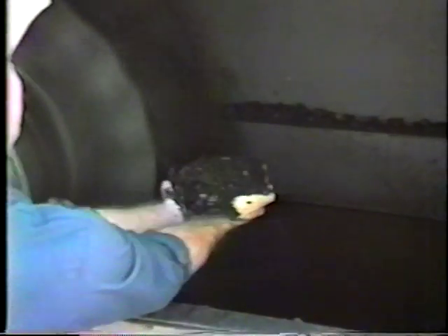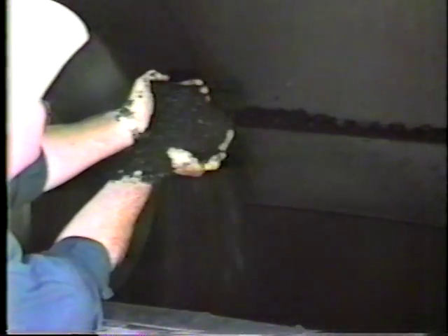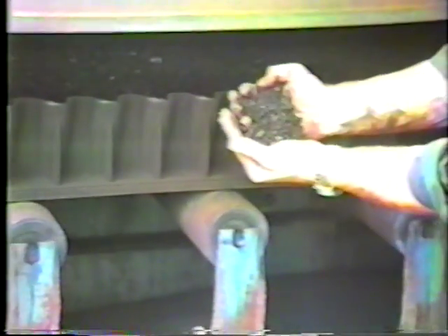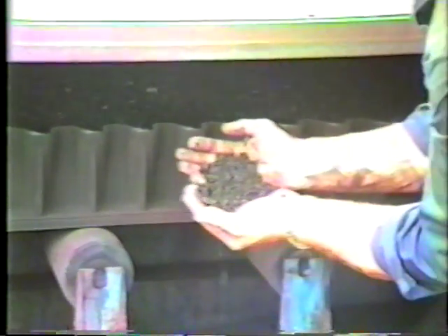The Williams impactor has reduced the coal to 90% -1/8 inch at the rate of 60 tons per hour. The coal then drops into these storage bins shown in the background, prior to feeding to the Williams pulverizers shown in the foreground. We are now looking at a gravimetric feeder which is feeding each pulverizer at a rate of 7.5 to 10 tons per hour, resulting in a total production in excess of 30 tons per hour.